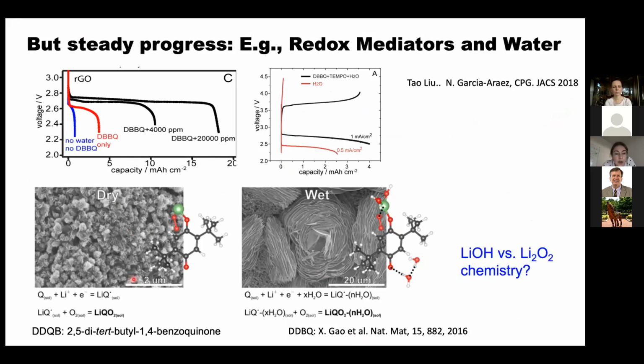And this is just work of ours, and also some earlier work by Peter Bruce in the UK, showing that if you use these redox mediators, you can take these large lithium peroxide crystals, and on charge you can oxidize them with an oxidized form of TEMPO, or in discharge you can react the oxygen with the DBBQ, which is a quinone molecule, and basically control the sizes of the crystals and where you actually do the chemistry. And so, there's steady progress. And so I think it's very much watch this space.